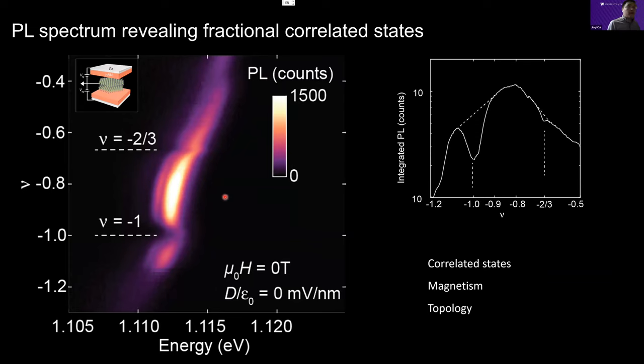Okay. So now we start to perform photoluminescence spectroscopy of a sample, and when changing doping and using a spectrometer to collect the energy resolved photoluminescence, we can actually see that if we dope the system at a fractional or integer filling of the Moiré superlattice, the trion population decreased. And that can be visualized very clearly when you integrate those PL emissions together and collapse this figure into a single curve on the right-hand side.